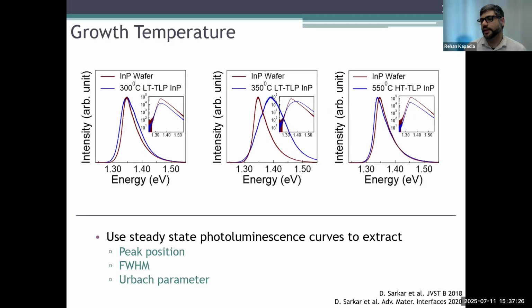And so what we did was a growth study where we looked at the growth at 550, 350, and 300, and then we just used photoluminescence, where we looked at the intensity of the emitted light when we would shine a laser on it, and then looked at the spectrum of that as a proxy for quality. Very simply, you want your photoluminescence to have the right peak position, and you want it to have the smallest line width possible. So the peak position matters and the line width matters.